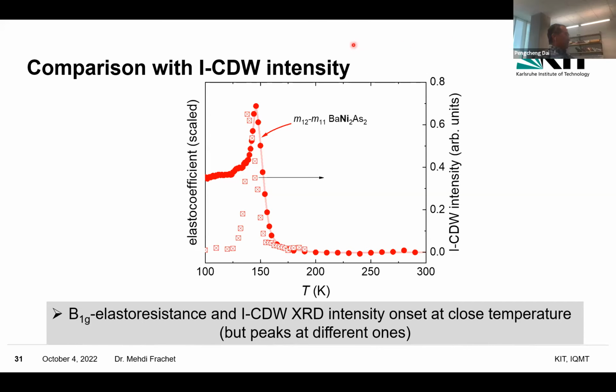So I was about now to compare this M11 minus M12 elastoresistance coefficient with the intensity of the incommensurate charge density wave, which is shown as this Bragg peak squared. You see that these two quantities peak at different temperatures. But the onset of the elastoresistance and the strong increase in this intensity occur at close temperatures.